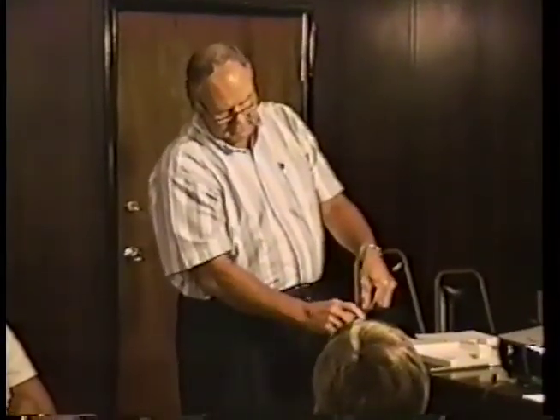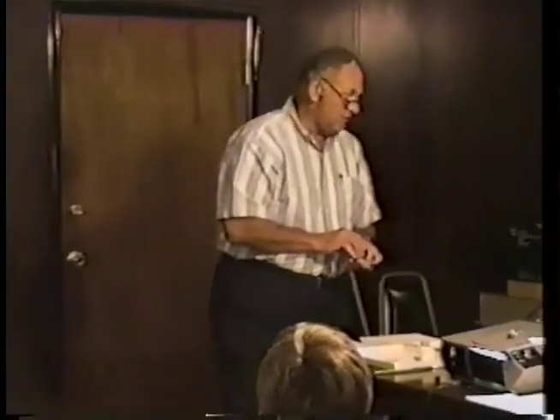Now some of you will recognize this is actually Fax film with the honeycomb pattern itself. It's one of the bars that's in that sample case. Like I said, it's like a fingerprint. So what we do is, with acetate tape, and I'll leave this with you if you want to use it, with acetate tape and acetone, $2 a can at your auto paint store, you can actually imprint the surface of the bore. We'll do that with some of these samples. With the acetone, and pressing a piece of this tape on there, you can actually lift an impression of that surface to the point that you can mount it and project it.